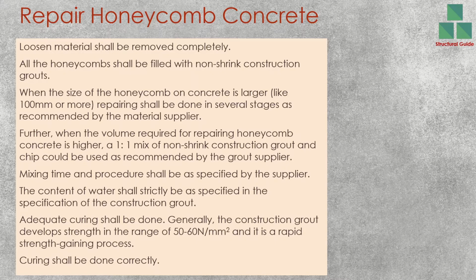That is because generally when concrete hardens, its volume reduces. It shrinks. But non-shrink grout's volume does not reduce. If you fill a cavity or a hole and its volume reduces from the top, the bond between the new concrete and the old concrete will not be there. So there will be a gap. Therefore, a concrete that does not reduce in volume shall be used. For that purpose, we are using the non-shrink construction grout.